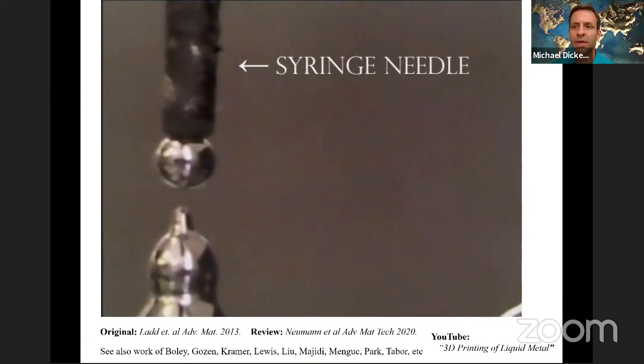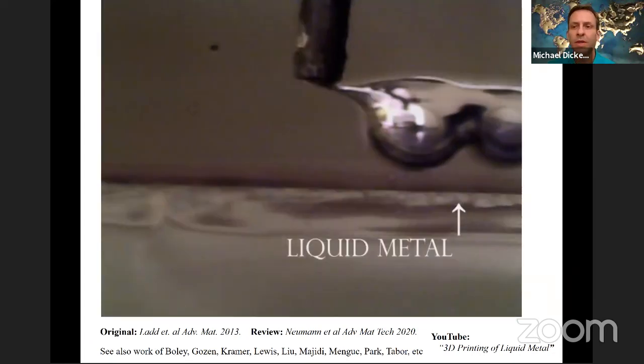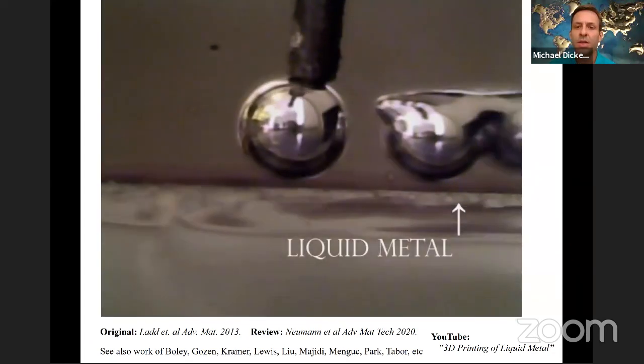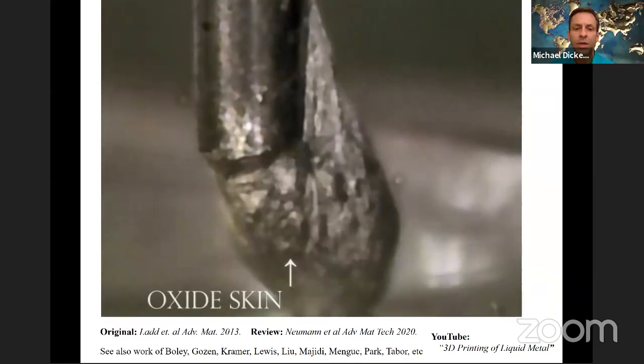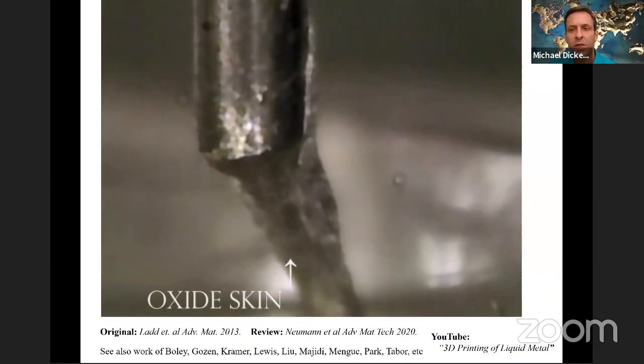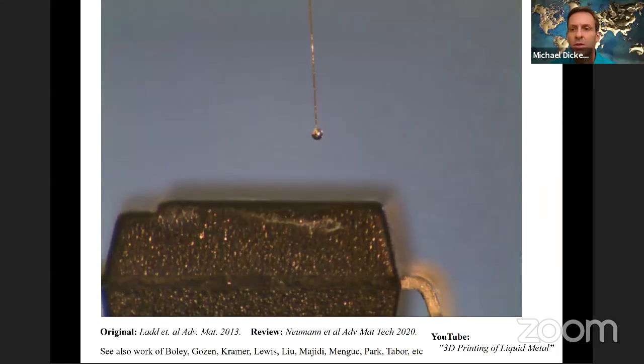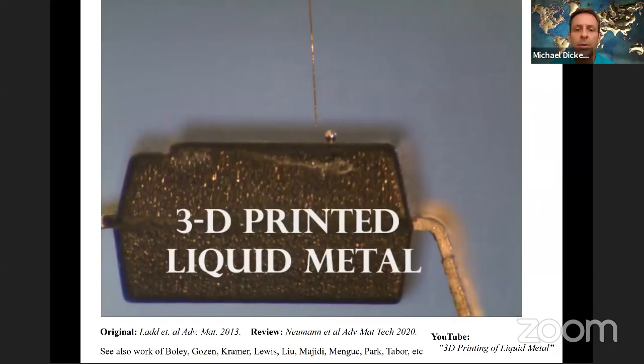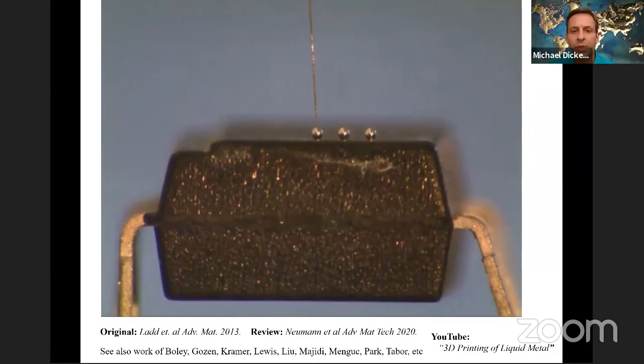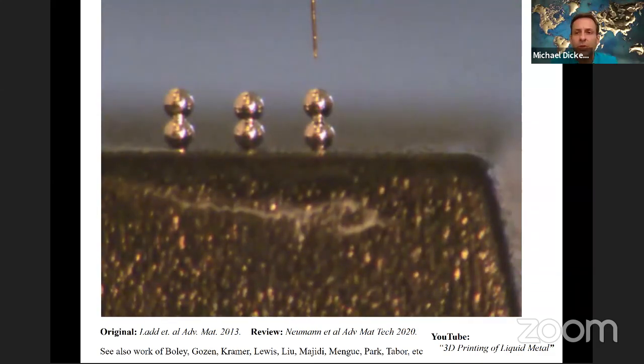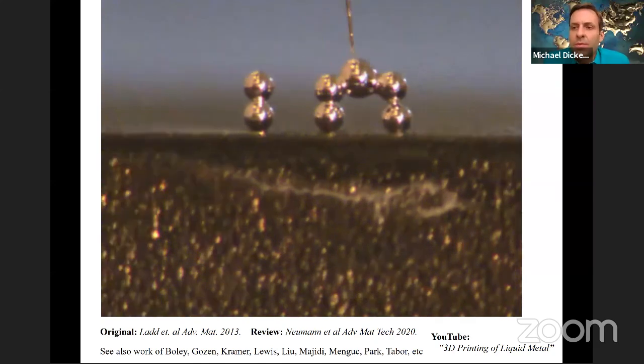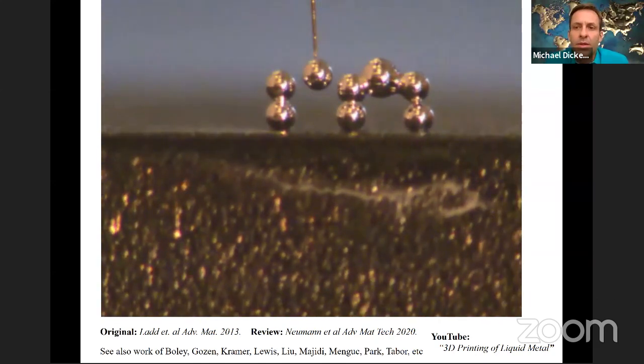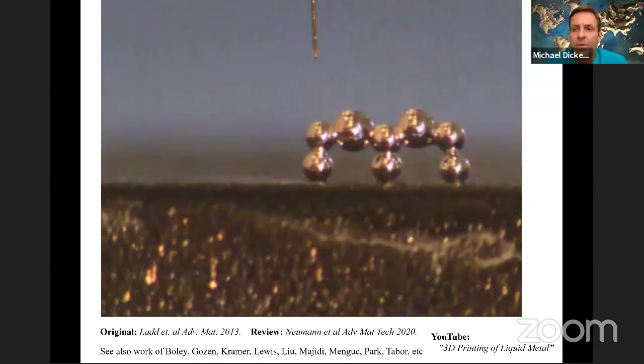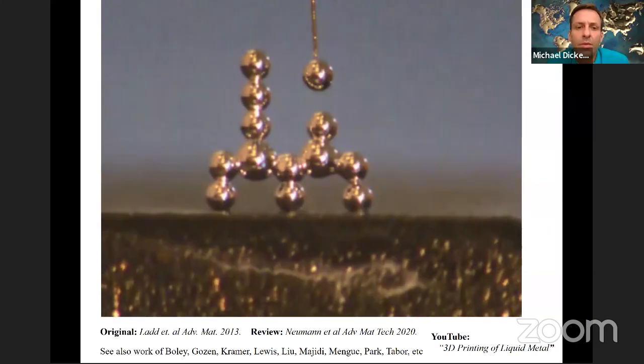So why am I making such a big deal about this oxide? Well, what it allows you to do is pattern the metal into shapes that would normally not be possible. So in this video, we show a syringe. We suck the liquid metal back into the syringe. You can see the oxide wrinkle. And we dispense the liquid metal from a syringe, and you can see that you can stack droplets. And so for the first time, you can actually 3D print metals truly at room temperature without any sintering.